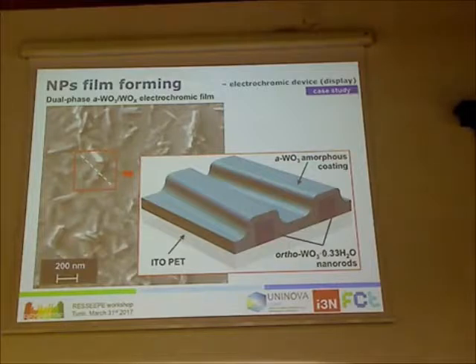Let's see an image of the resulting film, the SEM of the resulting film. This is the flexible foil with the transparent contact already there. You have the nanoparticles that were first sprayed on the substrate, and then you coat the particles to fix them to the substrate with a layer that is amorphous. But both are based on tungsten oxide. So this is the electrochromic dual layer, or dual phase layer.